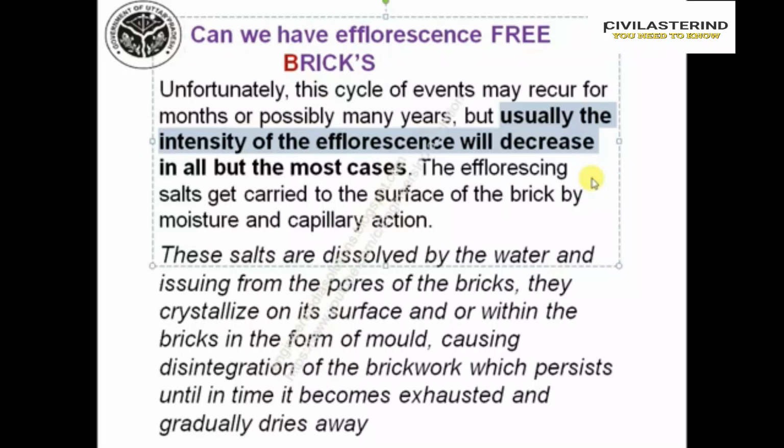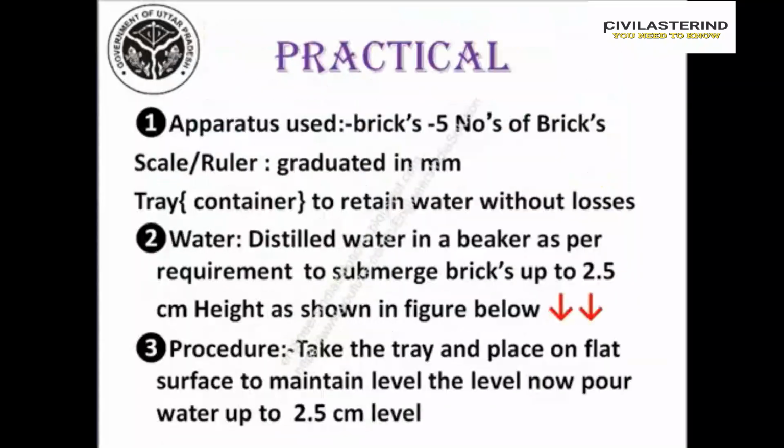So as far as the efflorescence is concerned, you can reduce it to quite a great extent so that you don't find it on the surface of your wall. But wherever it is present, as I said before, you have to use acetic acid, or if you want it from the market, you have Dr. Fix-It, which itself contains 5% acetic acid and can be used for brushing away the efflorescence and allowing it to dry.